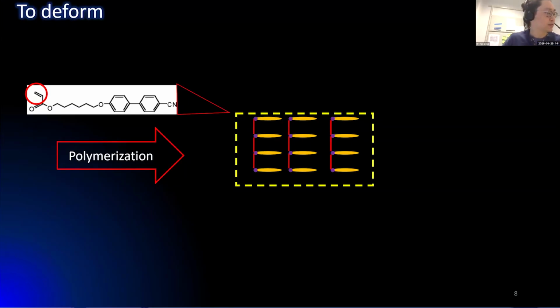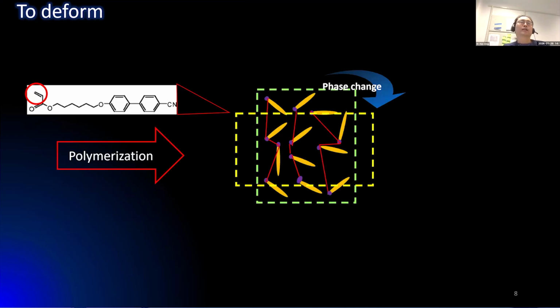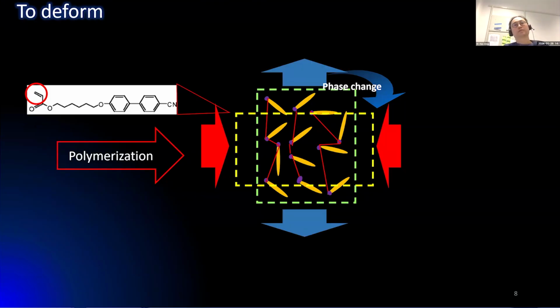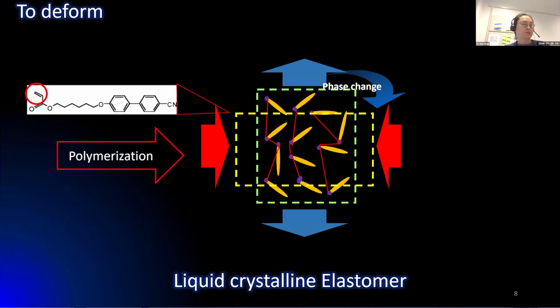Since it becomes a solid, it has a shape, but still preserves the liquid crystalline property, which means if you heat up the temperature, you heat up the structure, it becomes disorder and it will contract along the alignment direction, which is the liquid crystalline orientation direction, and expand to the other two directions. And in this way, we can use the light heating or heating to control the deformation, and we call this material liquid crystalline elastomer. So we apply the stimulus, deform,